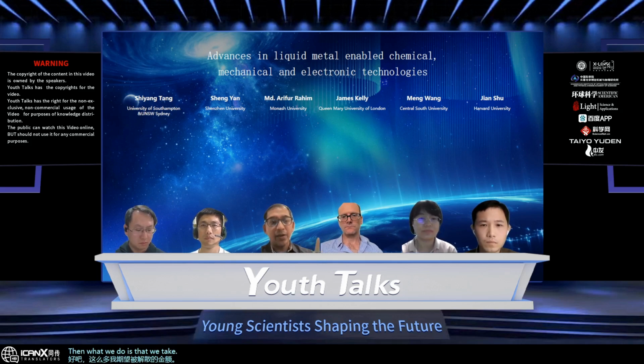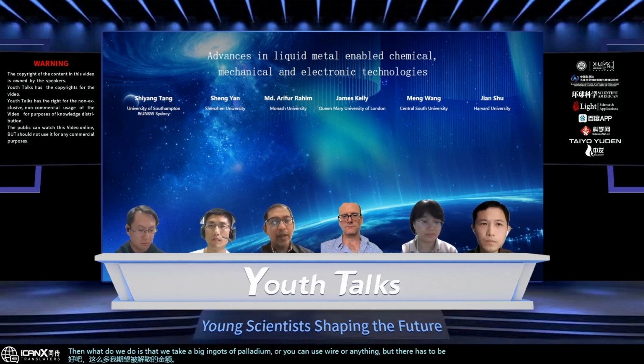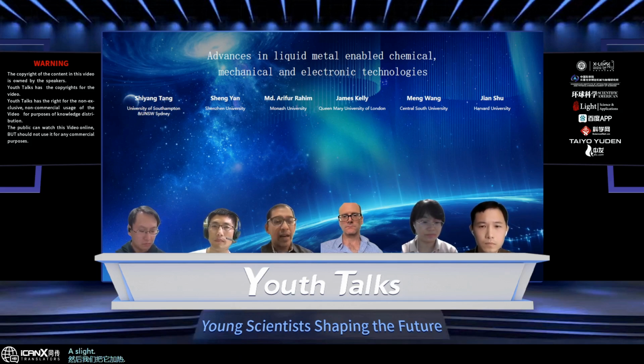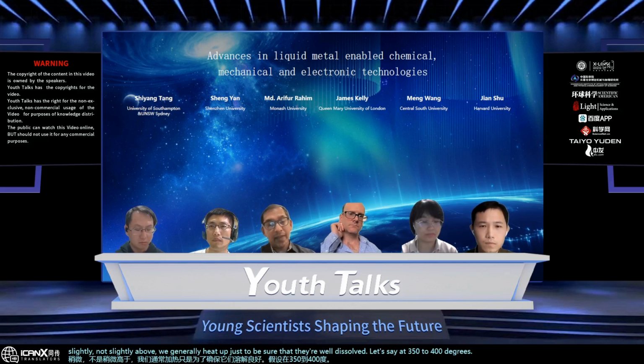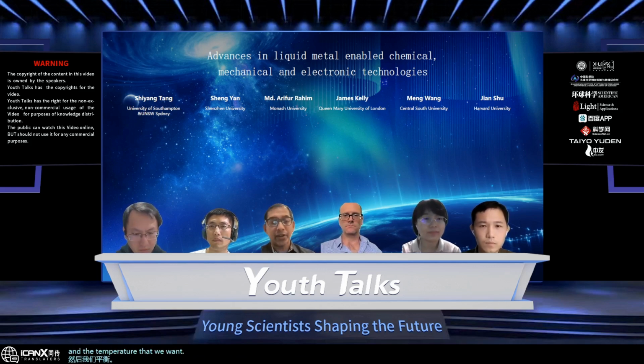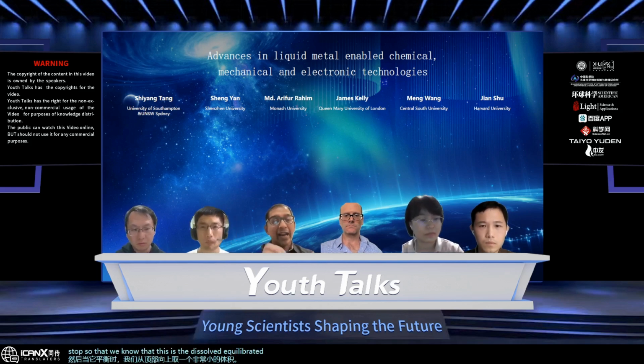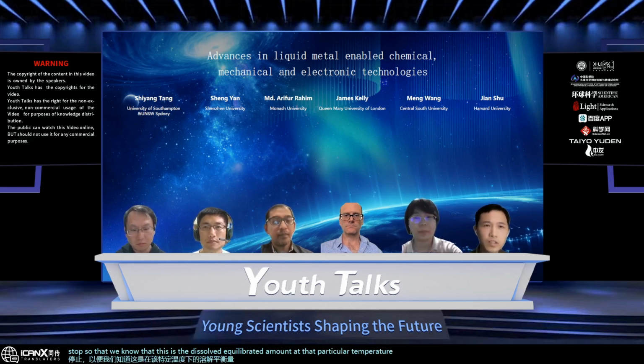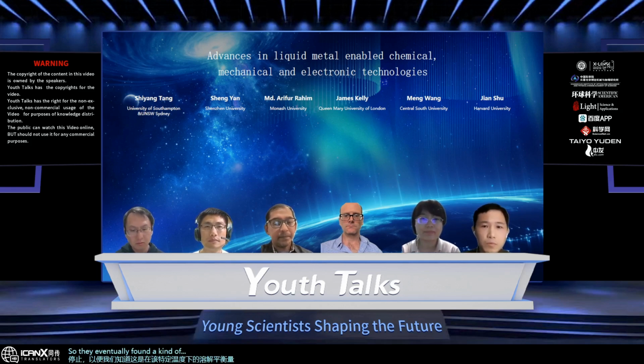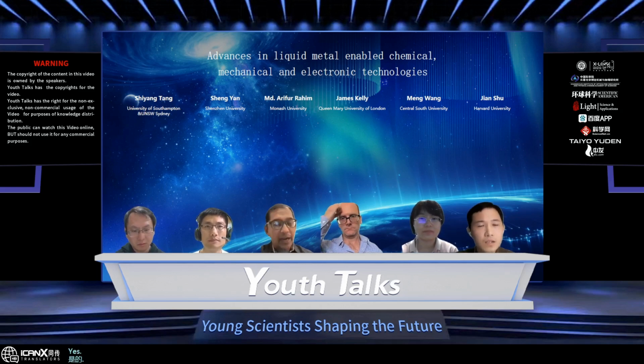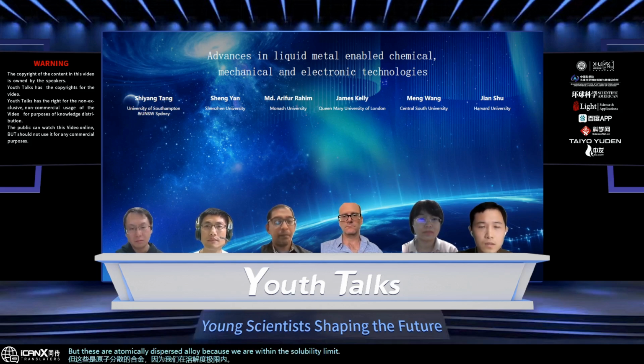Then we take big ingots of palladium, or you can use wire or anything, but they have to be pretty pure. Then we heat it up just to be sure that they're well dissolved, let's say at 350 to 400 degrees centigrade. Then we equilibrate at the temperature that we want the reaction to run. Generally, it's a pretty big amount that we initially prepare, a stock. When it equilibrates, we take a very small volume from the top of this stock, so that we know this is the dissolved equilibrated amount at that particular temperature. So eventually you form a kind of alloy, right? Yes. But these are atomically dispersed alloys because we are within the solubility limit.